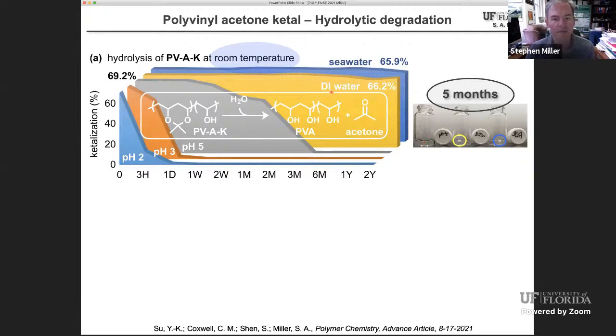So we continued with the experiment to understand if water and seawater are capable of hydrolyzing polyvinyl alcohol, this polyvinyl ketal made from polyvinyl alcohol. And the answer is probably yes. And you can see this 2-year data point. And yes, we ran this for 2 years before we finally submitted this paper. And if you believe these numbers, it seems to be about a 3% hydrolysis rate after 2 years. Okay, so we're probably changing the properties a little bit. Maybe it's speeding up a little bit with additional OH groups appearing in the polymer backbone.